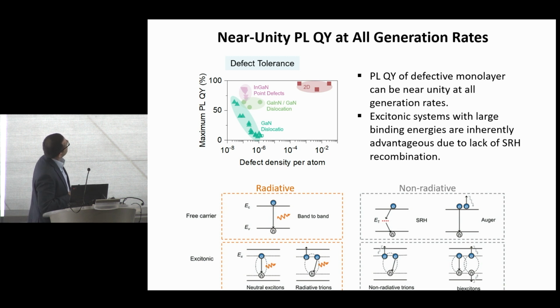So this slide summarizes what I just highlighted, that one way to look at the uniqueness of these 2D materials is to look at the maximum brightness that you can get versus defect density. And of course, gallium nitride can be very bright, but the tolerance to defects is very low. You have to have very low defect densities. In the case of 2D materials, despite having very high defect densities, and the processing being very naive, we have a lot of defects in these materials. We can get very bright materials. And I think that's really an advantageous property when you're thinking about integrating these things for monolithic 3D stacks where growth conditions are not going to be optimal for some of the III-V materials.